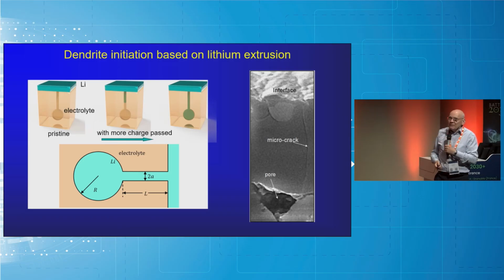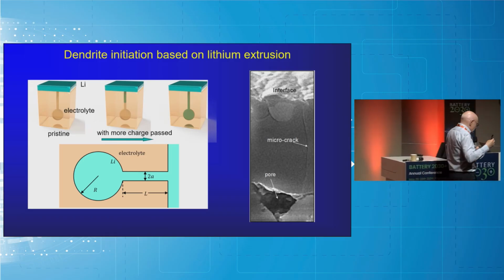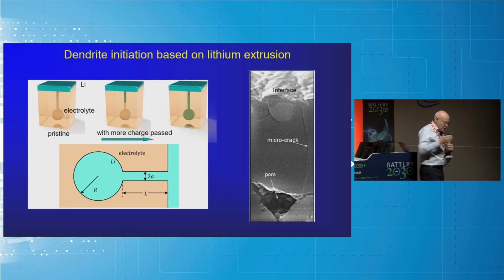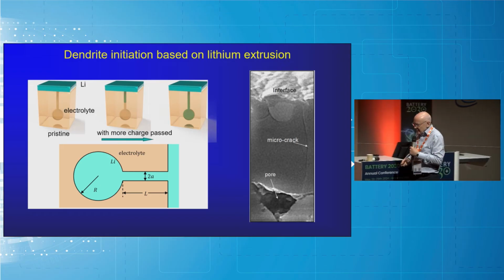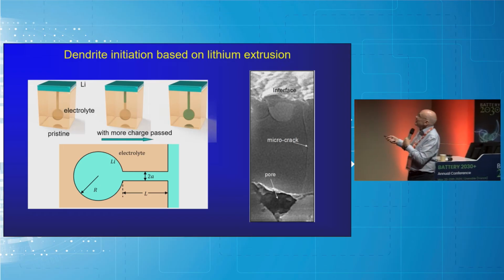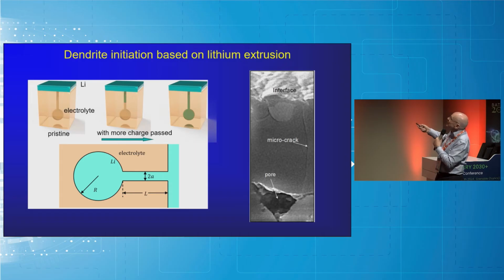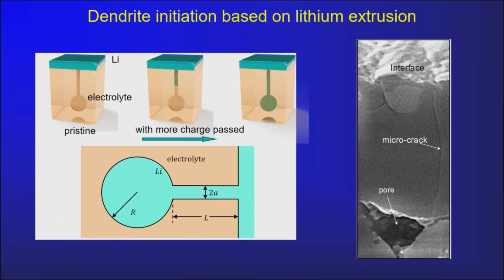Now, we've done a lot of FIB-SEM cross-sections of solid electrolytes with lithium metal anodes, and we see lots of features like this. So this is the lithium metal up here. This is the ceramic electrolyte. We see lots of features like this, these microcracks that connect crevices here to subsurface pores. So we represent that process by this in the model here.